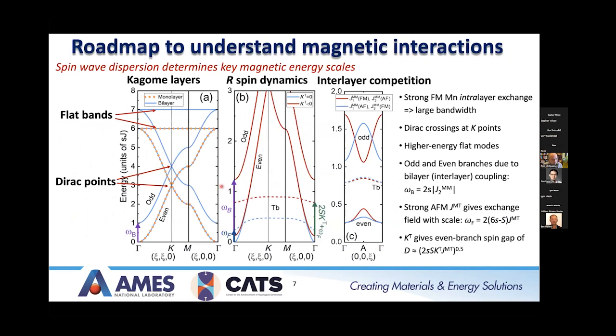Okay, so from that Hamiltonian we just built up, we can look at what we would expect in the magnon dispersion based on the Hamiltonian. So for the kagome layers, you get these nicely dispersing bands here because they're bilayers. So you have that bilayer splitting. Because they're bilayers, you actually get a splitting of these bands into what we call even and odd modes, and they're called even and odd depending on what gamma point you actually see them at. And you'll see that in the next slides.